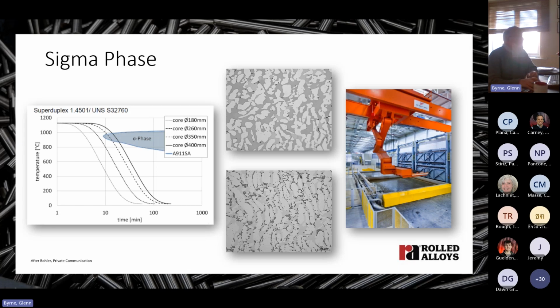But we find that sigma can form in three ways. It can form isothermally if the steel gets held in the temperature range between 650 and 1000 degrees C, where sigma forms, for a long enough period of time, then you'll get sigma in the parts. And the longer it spends in this phase field, you get more and more sigma. So if you just enter it, you get a small amount like you see here. You leave it longer, the particles grow and become more numerous, and you get a microstructure that you see here.